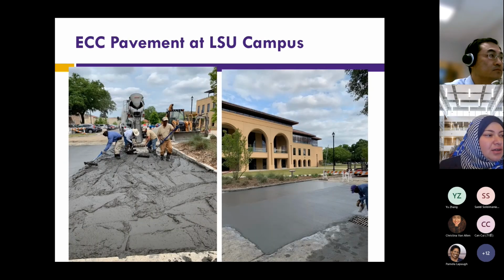This is the placement of ECC as pavement. And this part itself has a funny story because they wanted to repair that pavement with the low-cost ECC. We gave the contractor the M3 1.5 mix that I just talked to you about. But the contractor made a mistake and reduced the cement content even further, so we ended up with a mix that has a very low compressive strength. It's comparable to flexible pavements more than concrete pavements.